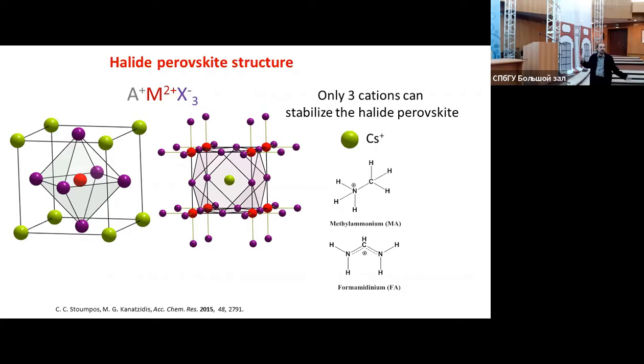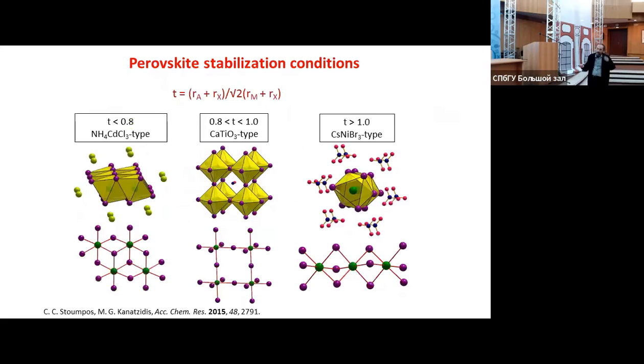For halide perovskites, we have a problem, because we can make them stable only by using three A-site cations. One is cesium, the largest cation in the periodic table. And then, because the periodic table is so small, we started doing the same thing with small organic cations. The cations that can fit in this pocket are the methylammonium cation and the formamidinium cation. And the reason why this is the case is this equation, the Goldschmidt tolerance factor equation. This is the ionic limit equation, which basically considers all the atoms to be ions, and then this is the condition for the ions not to touch, and this dictates which structure will be more stable.